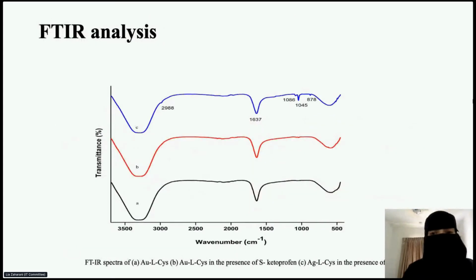With the FTIR analysis, the spectrum of L-Cysteine capped gold nanoparticle shows a very broad band. This band, 3000 to 3500, corresponds to the OH stretching and NH3 stretching, and this peak corresponds to the C=O stretching. So when we introduce S-Ketoprofen, we get the same spectrum.